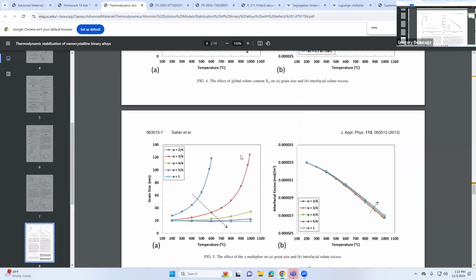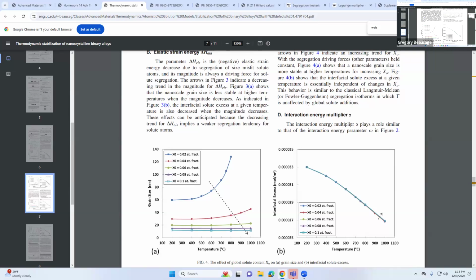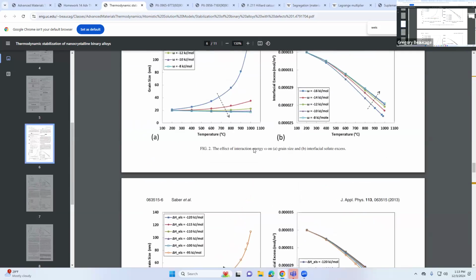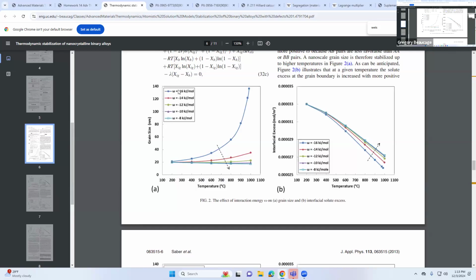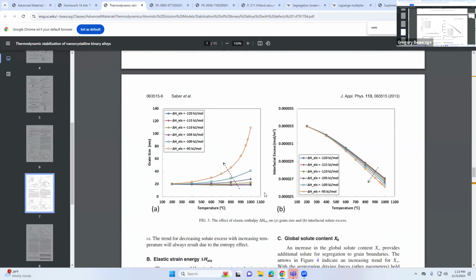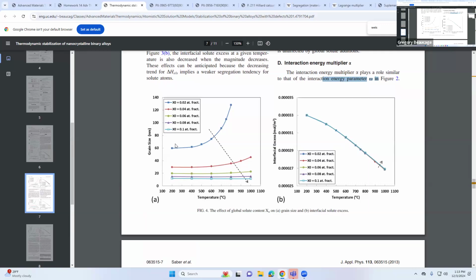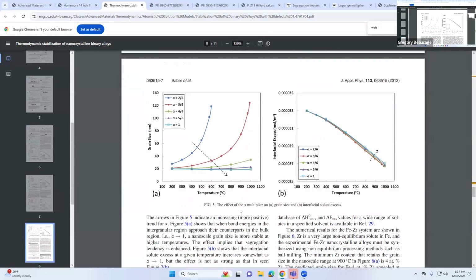This is figure 5, right? Interaction energy multiplier plays a role similar to that interaction energy parameter omega in figure 2. That's true, it's the same as figure 2. As this becomes more athermal, then you get more stable, so that there's no energetic difference between the dispersed phase and the matrix phase. That means the elastic energy just drives it. So maybe you can make the same argument here, that when you remove the driving force to go to the interface, the elastic energy becomes dominant and that does it. But that doesn't exactly make sense to me.